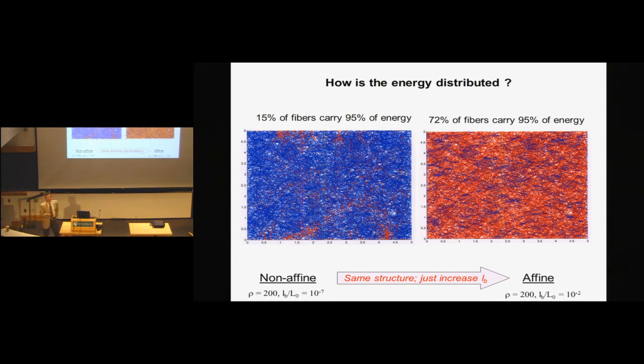Here is a network realization, both on left and on the right. It's exactly the same network. On the left side, I use fibers which are really floppy in bending. Okay, so LB is small. On the right side, exactly the same network, the geometry is identical. I use fibers which are stiff in bending. The colors represent how I store energy. Okay? So in this case, when fibers are floppy in bending, that is, I'm in the non-affine range, the network behaves like a really heterogeneous material. 15% of the fibers carry 95% of the energy. Most of them are blue.